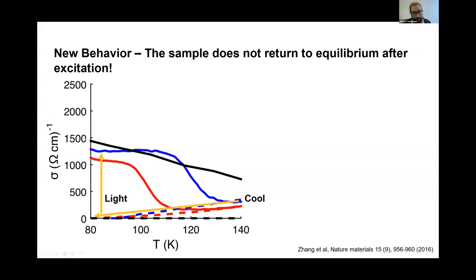And this black curve up here, I should show you, this black curve is the conductivity of the pristine, unstrained metallic phase. So this is the conductivity of essentially bulk LCMO. And so the conductivity jumps up almost to the bulk level. Then, if you heat the material, the conductivity goes back down to its insulating state around 120K. And by 140K, the material has, at least in terms of electrical conductivity, returned to the insulating state.